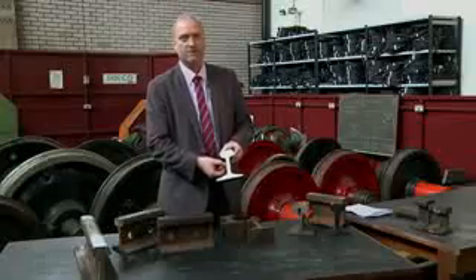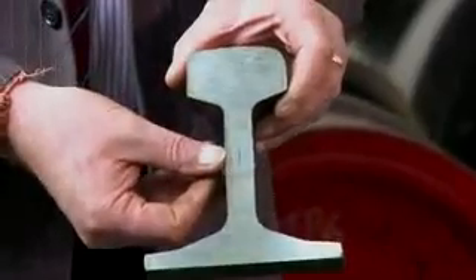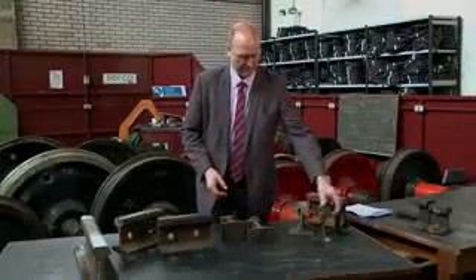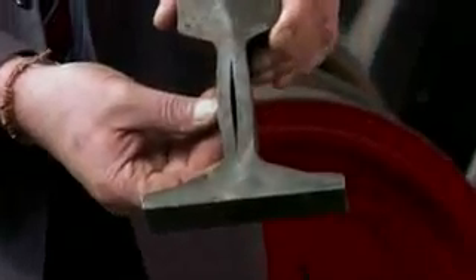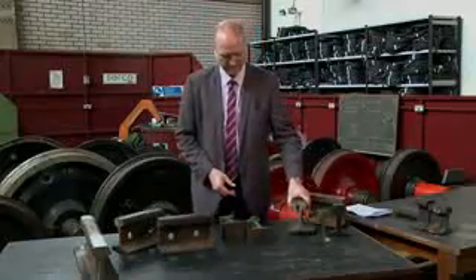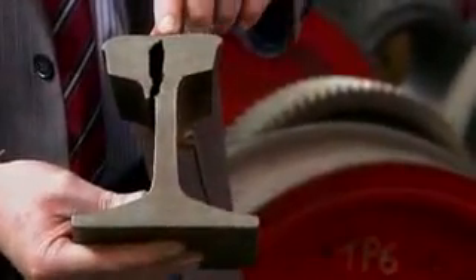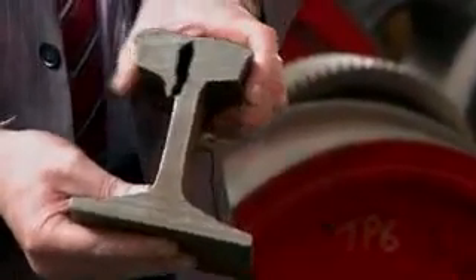Plastic deformation is another thing we see where the rails degrade. This is where the rails are physically deformed. They are spread, the rail steel itself is distorted and deformed under traffic. You can see the start of a small split within the middle of the web. These will propagate under traffic if not managed. They will grow to a larger size, the split will open up, and in extreme cases can result in a piece of the rail becoming detached. Most of our defects of this type occur in older rails where there are either inclusions or impurities within the rail steel which form a point of weakness which under repeated loading will cause the rail to fail.